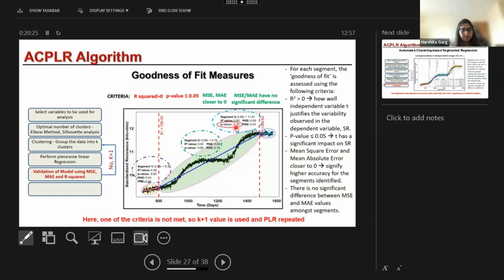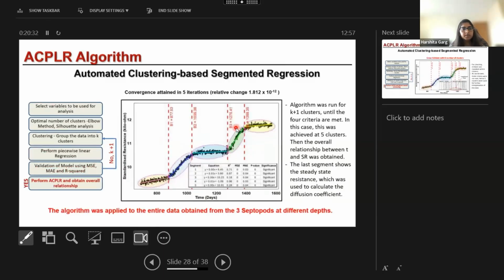So the algorithm reinitializes until all the 4 criteria are met. Once all the 4 criteria are met, it converges the clusters and provides us the correct location of the clusters and the number of clusters. Here we can see that the algorithm was run until all the criteria were met, and 5 clusters were obtained. The intersection point of the last two segments is considered as the time taken to reach the steady state condition and the steady state resistance value, which are two of the parameters to assess the performance.